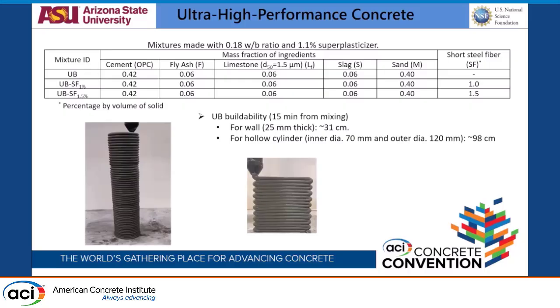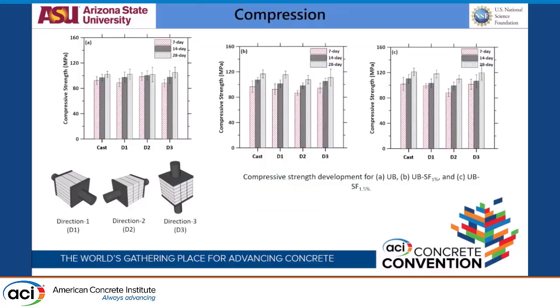We added 1% and 1.5% by volume of steel fiber. The steel fiber is a Bekaert fiber that's 13 mm in length and 0.2 mm in diameter. Shown below in the two pictures are the buildability tests for these mixes, done just after 15 minutes of mixing. For wall elements of 25 mm thickness, shown on the right, we could go up to 31 to 32 centimeters after 15 minutes of mixing. For cylinder elements with a 7 cm inner diameter and 12 cm outer diameter, we reached around a meter height without any failure. We did not go beyond the meter. So these mixes are printable and buildable.